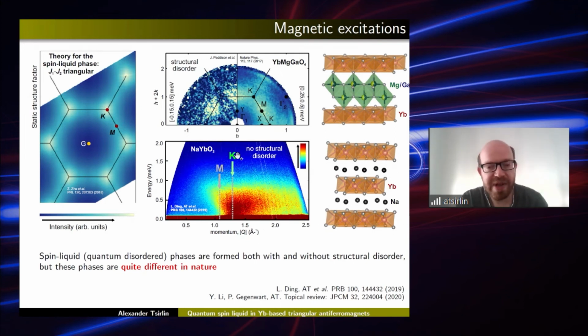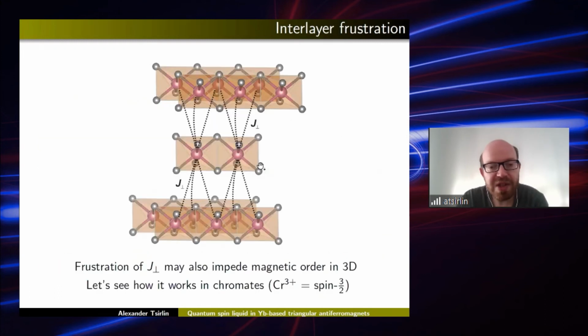And in the last couple of minutes, let me explain to you why. The reason is that in all these materials, the triangular layers are displaced with respect to each other, right? They are displaced in such a way that each ytterbium ion interacts with 3 ions of the neighboring layer, right? So they're not stacked perfectly on top of each other, but there is a shift, and therefore there are several interlayer couplings like that, and they obviously are going to cause some interlayer frustration because these 3 couplings cannot be satisfied at the same time.